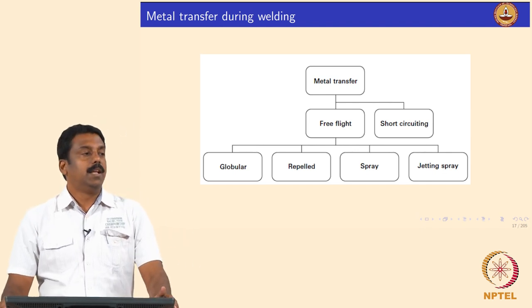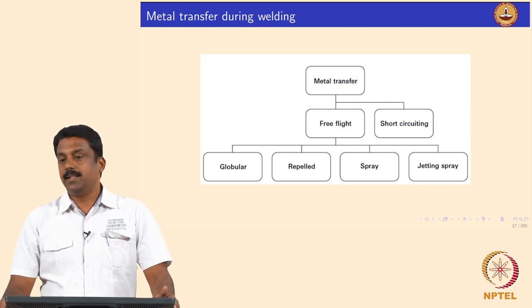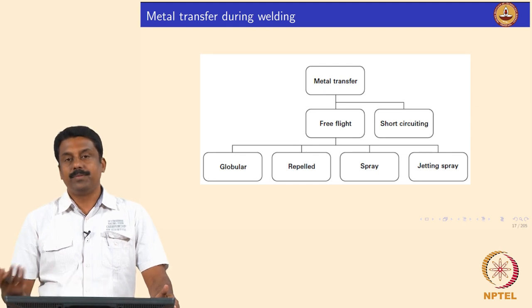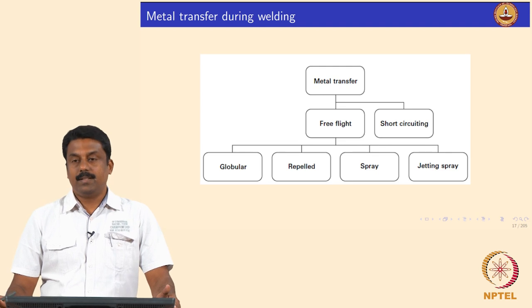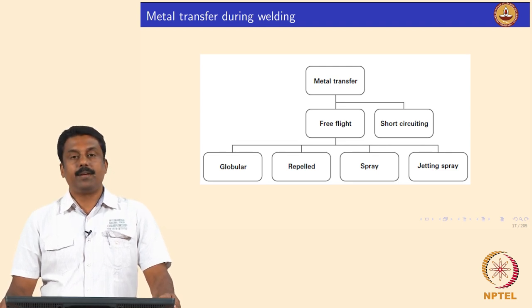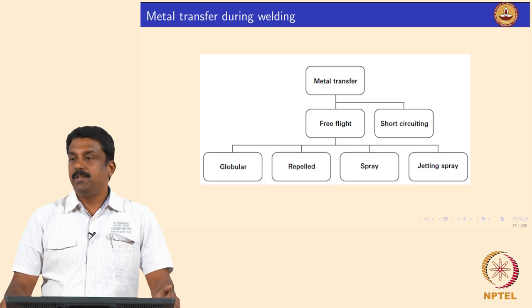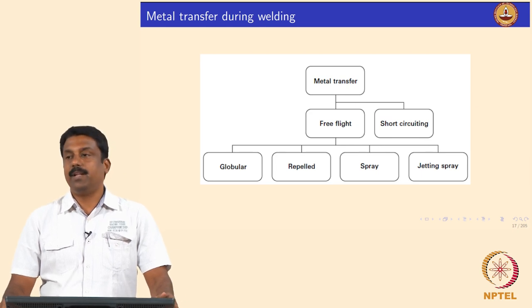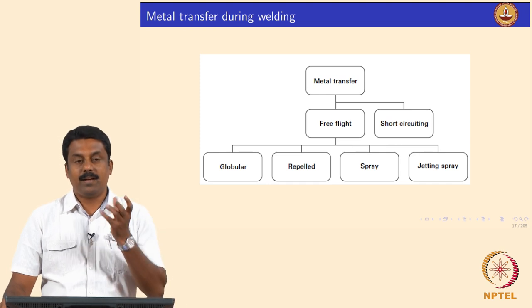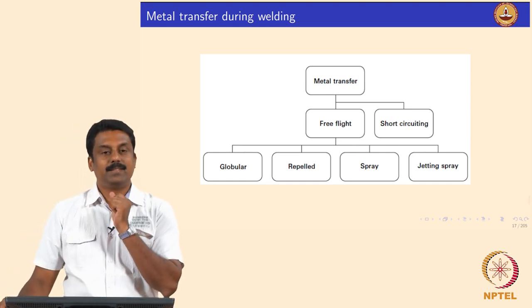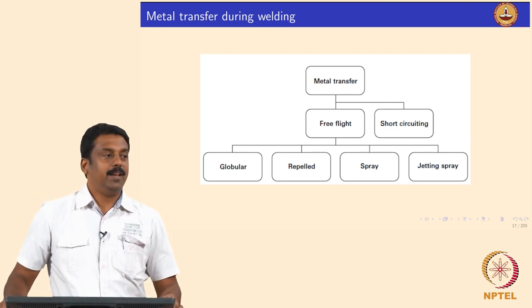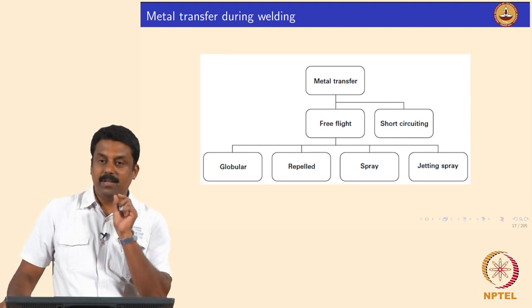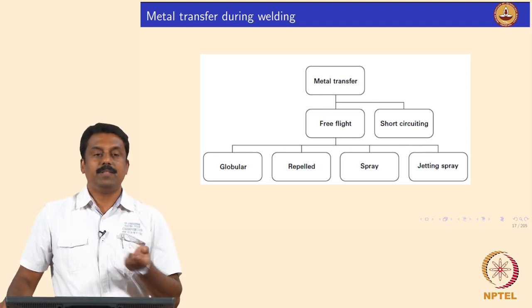Based on the force balance, the droplet may be transferred in various modes. In most cases, the diameter of the droplet and the frequency of droplet transfer are determined by which force is rate-controlling. If gravity is rate-controlling, the droplet will be transferred with high mass — like a globe — with higher volume. If Lorentz force is rate-controlling, you can transfer at very small diameter and at much higher frequencies.